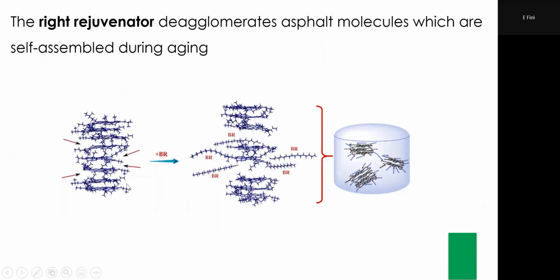If you look at the first figure on the left, these are aged asphaltenes. When the molecules of asphalt age, you can see some of our publications on the aging mechanism. What happens is your asphalt molecules become oxidized, whether it's fused aromatics or the alkane chain, and as they get oxidized, they become more polar. Increase of polarity makes them adhere or bind together more often, and you end up having these stacks of asphaltene, for instance. Asphaltenes tend to have pi stacking, and as we get more and more of them, you can see the layers build up to become a large aggregate. We're going to have aggregated asphaltenes here.